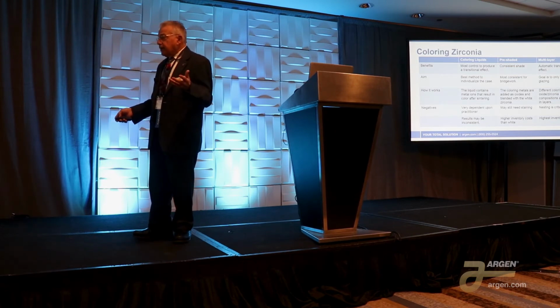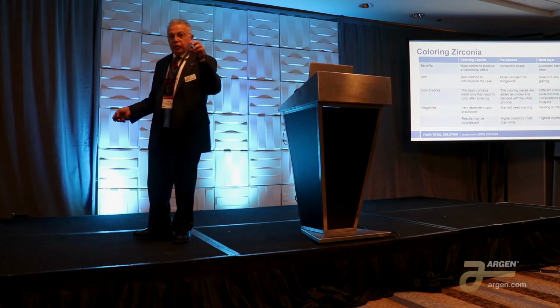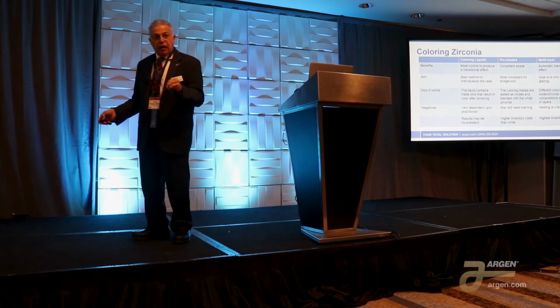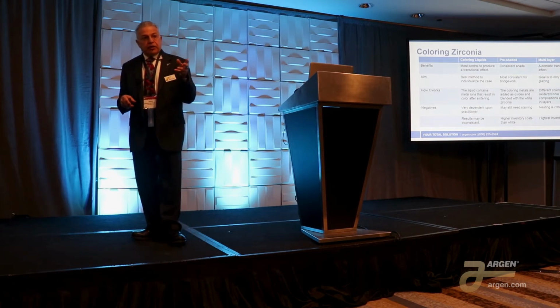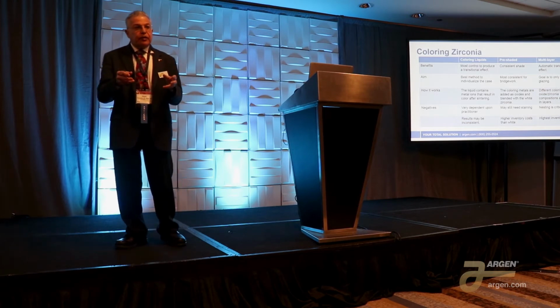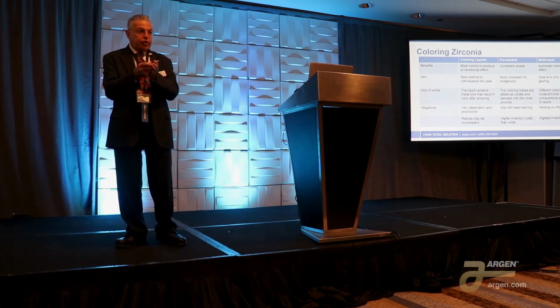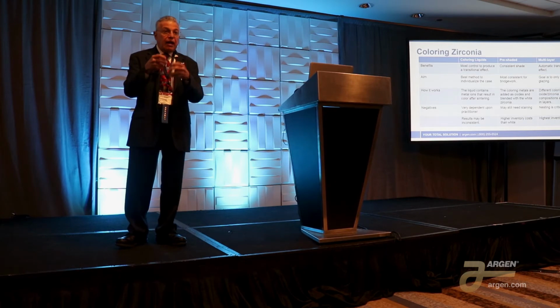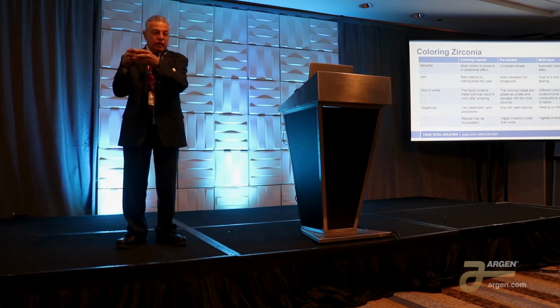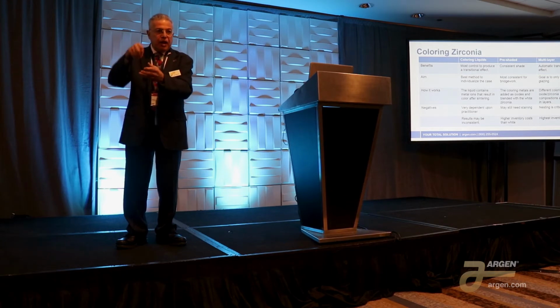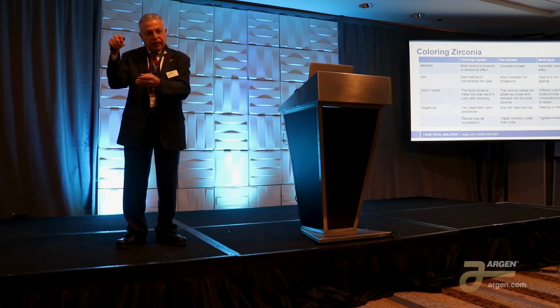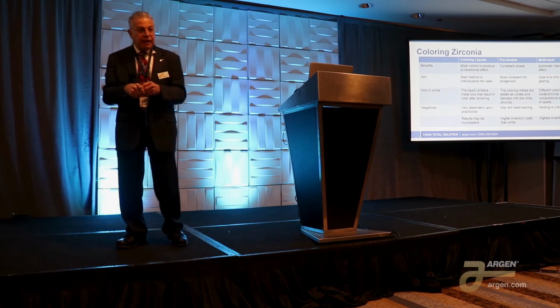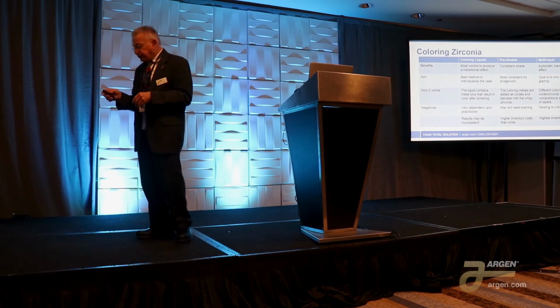The negative about this is that it's very dependent upon the practitioner, whoever is doing the dipping. You could get two restorations that are identical, and if you do it at two different times, the shade may not match. In order to address that, in our digital center, we use these little jewelry cleaners, and we dip the units in at the same time and take them out at the same time, so that the shading is going to be identical amongst those units.